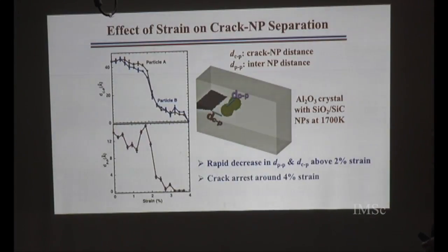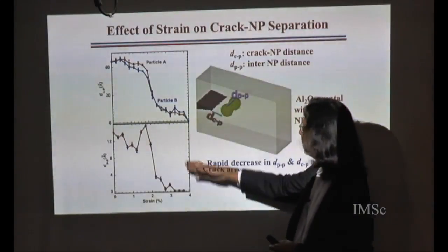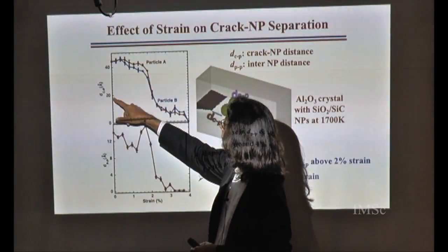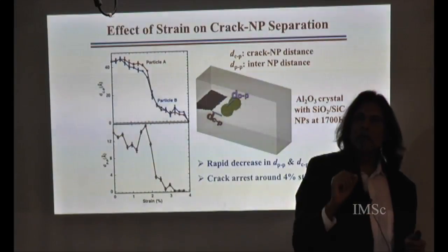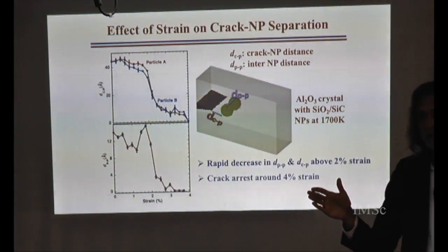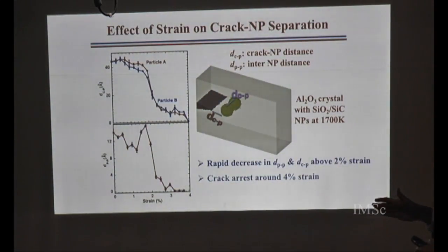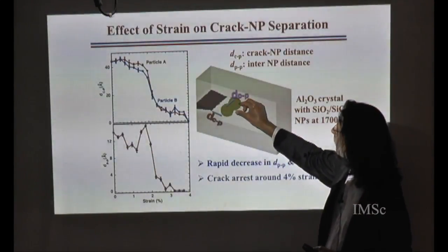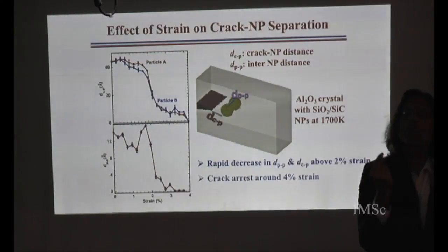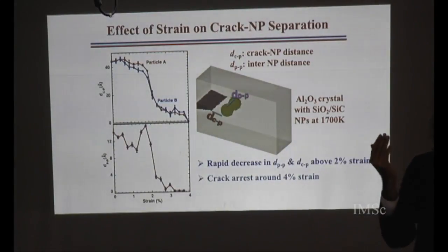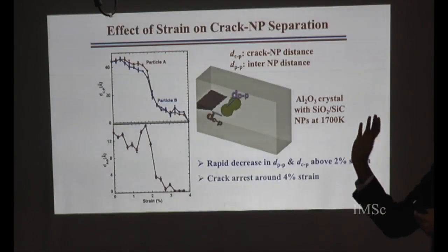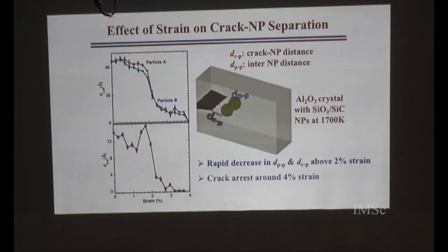From here you can see that even at a very small strain like 2%, the separation between the crack and the nanoparticle decreases very rapidly. At the same time, the distance between nanoparticles is also shrinking, so there is a coalescence of these nanoparticles. I will describe these processes.